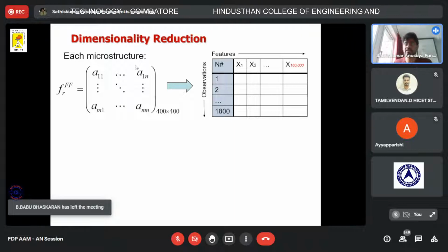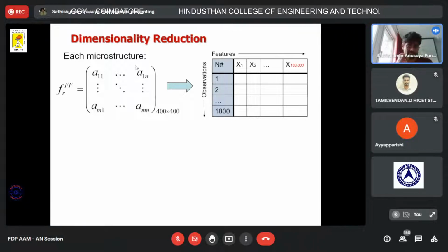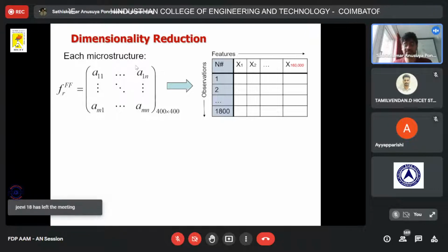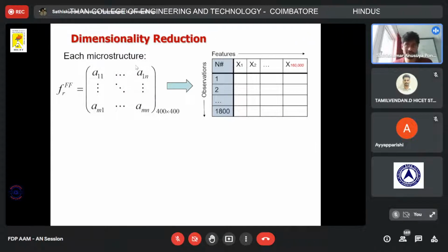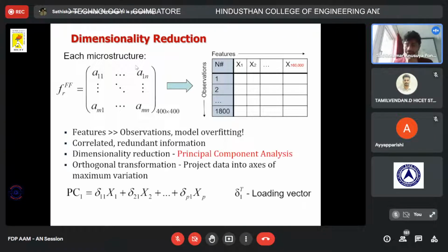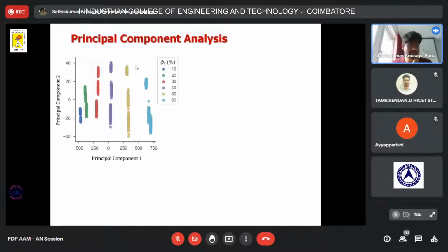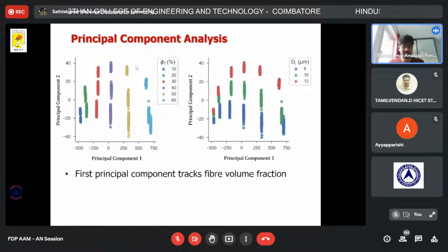In here, instead of having a matrix of size 400 by 400, meaning we divide each image into 400 by 400 pixels, which means the size of the image would be 160,000, and that is your number of input variables for the machine learning model for one image, which is quite complicated. So what we do is use dimensionality reduction with principal component analysis, and we obtain a set of reduced numbers that represent the actual image. That is what principal component analysis is. And so you see some of the results of the principal component analysis.